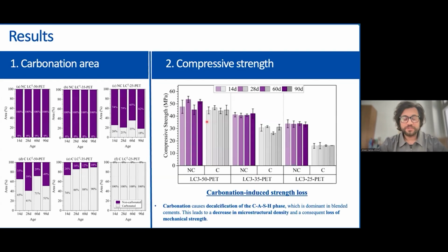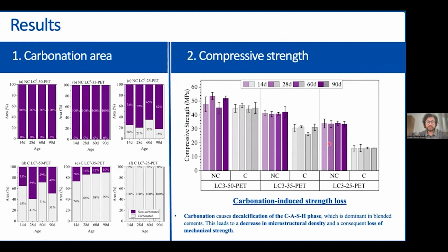And another trend that you see is that LC3-50 shows high strength compared to LC3-35 and LC3-25, and this is because we are reducing the clinker content significantly over these three formulations. At the same time, it's also very interesting to know that the difference between the carbonated and non-carbonated is clear here, that the carbonation is leading to loss in strength, but here it's not really clear, because when we try to crush the LC3-50 and 35 samples, since they are not fully carbonated, the core is the one that is strong and in the middle, so that is leading to a lot of resistance when we try to crush under compressive load.